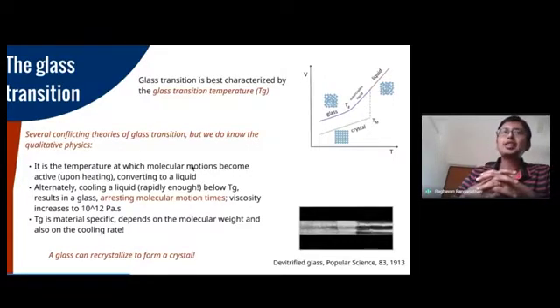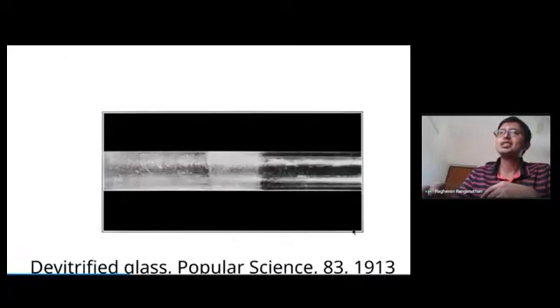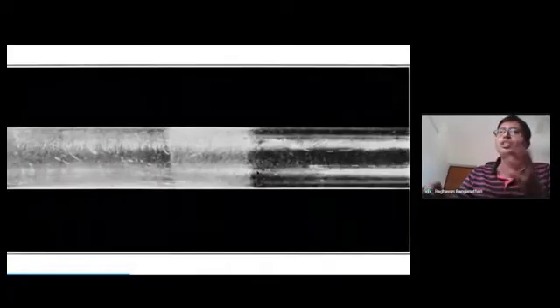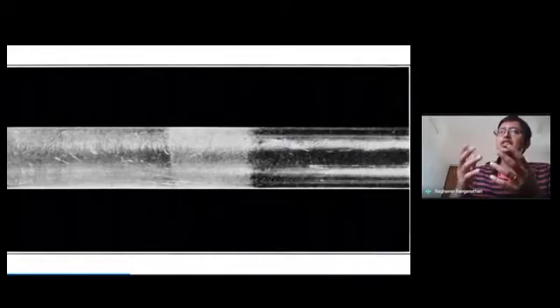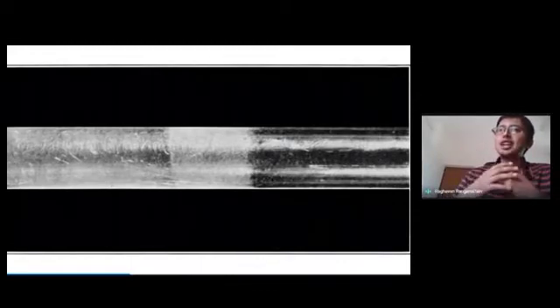And finally, when talking about the glass transition and glass transition physics, what's very interesting is a used glass can actually recrystallize and form a crystal. So this is very evident in laboratory equipment where you say have a glass vial or a glass beaker, and then you leave it unattended for some time, or maybe use it for a sufficiently long time. Based on some thermal fluctuations, the glass can become devitrified. A part of it can basically crystallize, and of course that loses its transparency. The crystal diffracts light, and it behaves as an opaque solid.